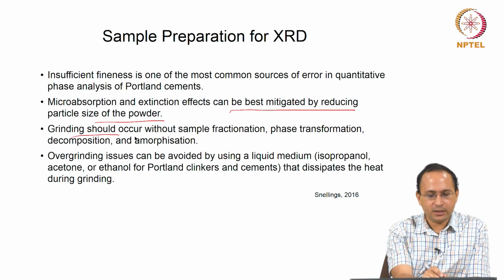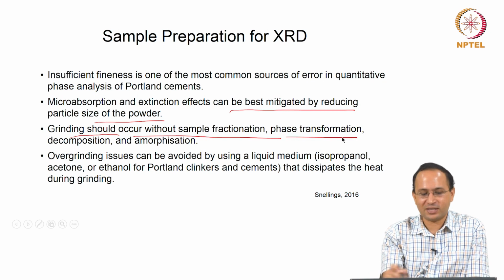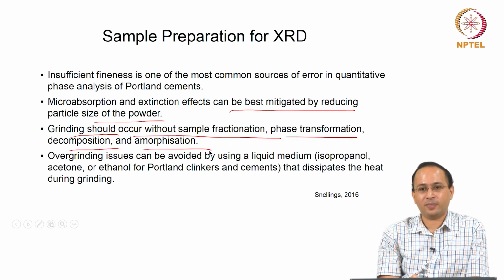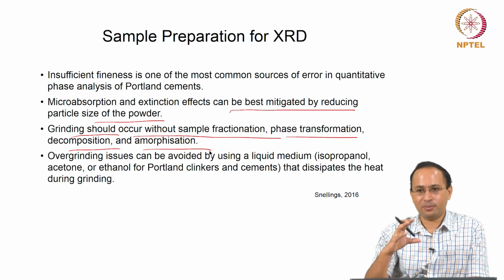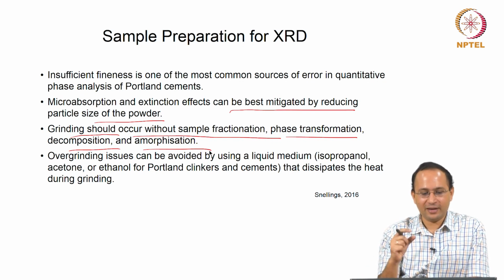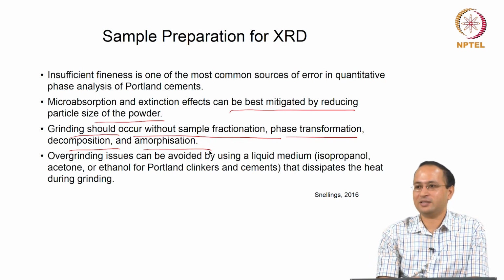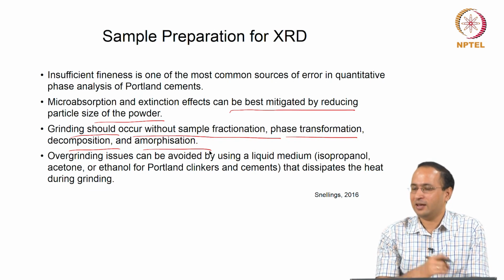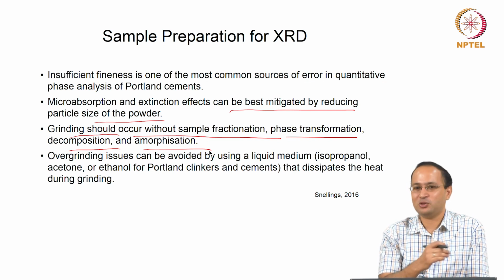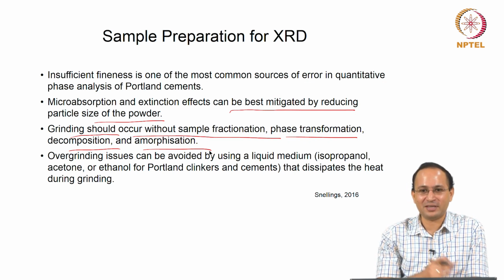Grinding should occur without sample fractionation, phase transformation, decomposition, or amorphization. You have to make sure of that. So, you have a sample, you grind, and if you analyze your sample before and after grinding, you should not see these phase transformations, because otherwise that means you have changed the sample. Grinding should not lead to decomposition of a phase. We saw that when you grind too much or use mechanical grinding, depending on the temperature rise, you may affect the phases. Those things you have to keep in mind, because that will change your phase assemblage. Amorphization.